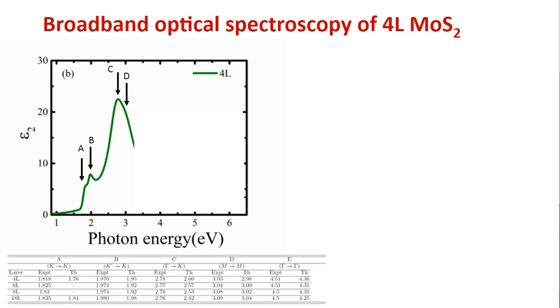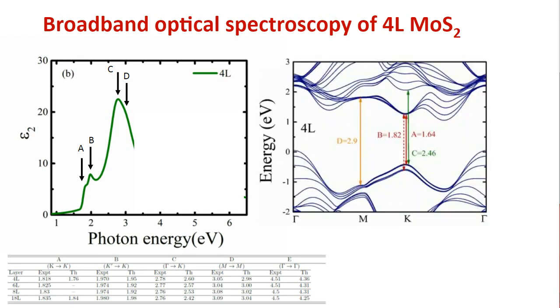And by that time, we were also doing a significant amount of band structure calculations, like I was showing, all the spaghetti lines. Again, lots of vertical lines that you can see here. And those lines help us to assign the optical transitions. We have assigned the A transition, the B transition, the C, and the D here. These are all direct transitions, some close to the K point, some close to the M point. But then we proceeded, hey, let's do the broadband spectra.